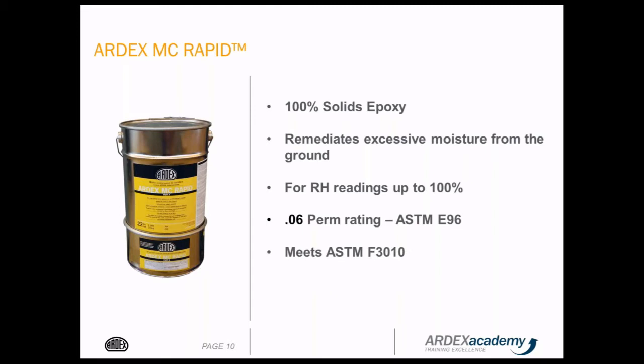When you look at ASTM F3010, this standard is the standard specification for 100% solids epoxy moisture remediation systems. And to qualify for that standard, one of the criteria is meeting the perm rating that they establish. The standard specification for a vapor retarder that goes underneath a concrete slab, whether it's on grade or below grade, is 0.1 perms.